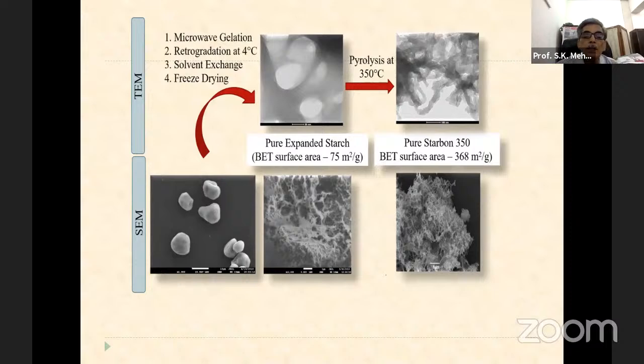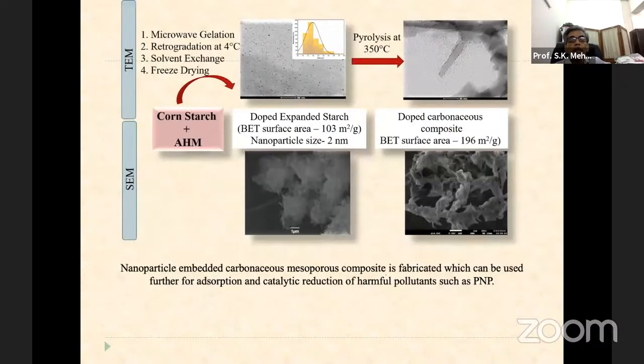And the first one will give you pure expanded starch created from biomass, and then the pure starbon, which was created, has a BET surface area of 368 meters squared per gram. And you can see even the SEM shows a very nice porous material. So this is again mixing of both cornstarch and the second one, AHM, which was prepared, and you can again do the pyrolysis, and you get the expanded starch. You have the dopant, carbonaceous dopant, when you have the molybdenum particles put in this. So this is the doped one, and here the SEM also shows more surface area. So a nanoparticle-embedded carbonaceous mesoporous composite is fabricated, which can be used for further adsorption and catalytic reduction of